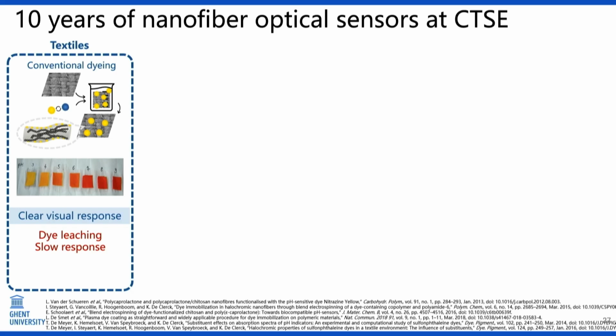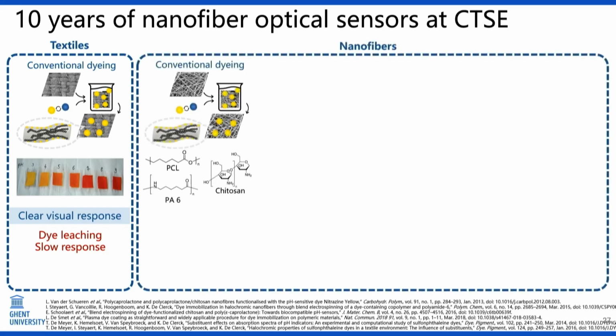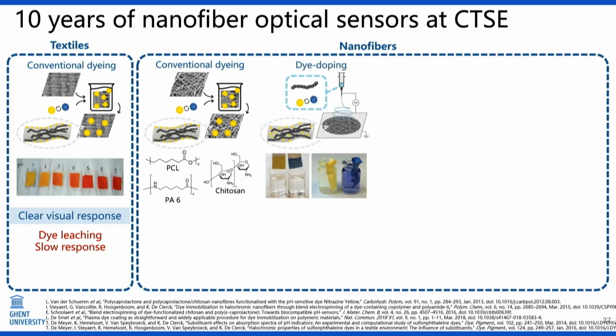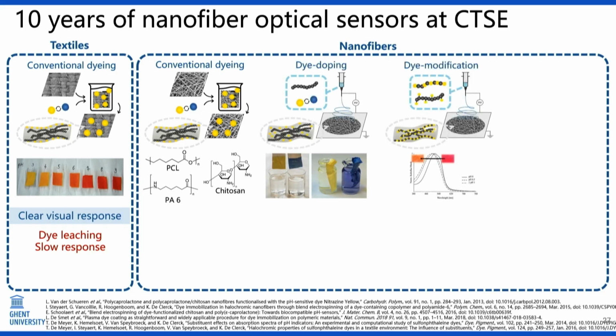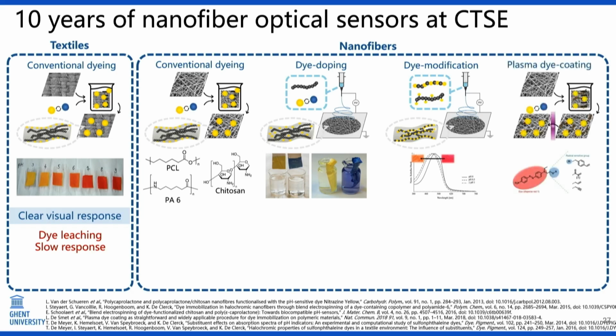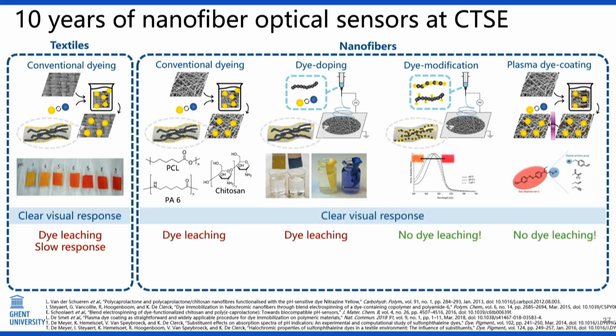The slow response time was quickly seen to be improved by reducing the fiber diameter, already for the traditional textiles. Then, of course, the next step is to go to nanofibers to decrease the response time. We tried different strategies, going from conventional dyeing of nanofibers, dye doping of the nanofiber solutions, all the way to dye modification of the polymers, which are then spun, and also post-spinning modifications with dyes through plasma treatments. They all work well and give clear visual chromic materials, but if you want no dye leaching, then we need a covalent bond between dye and the polymer.